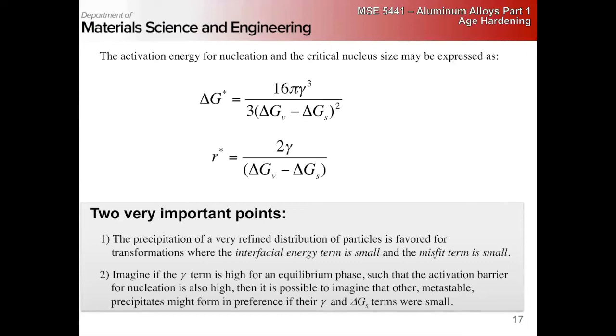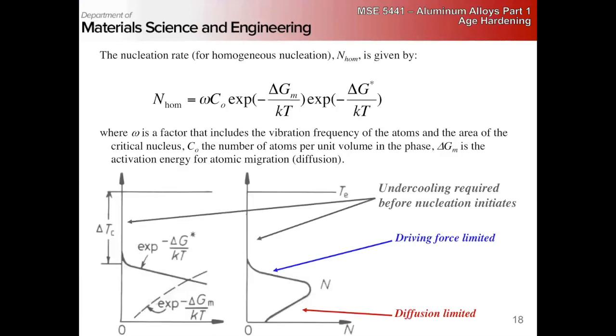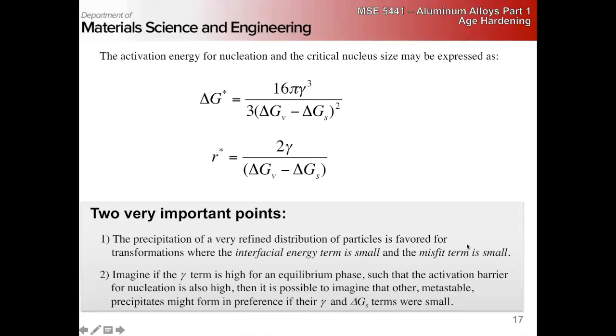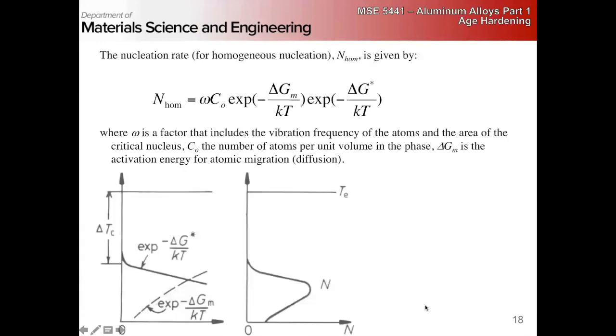So it's possible to create a situation where maybe other metastable precipitates form. Metastable being that they are not the thermodynamically predicted phase at equilibrium. But they form in preference to the equilibrium phase because the surface energy and strain terms were small, even though their volumetric contribution was not quite as large. And the reason I'm bringing this up is because this is exactly what happens in the aluminum alloys that we're going to look at.